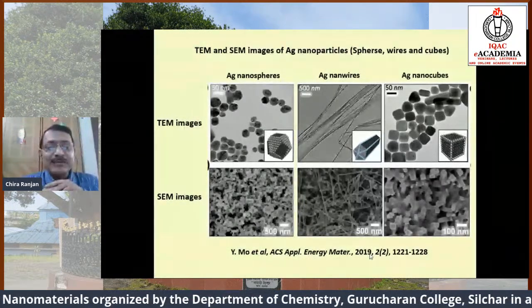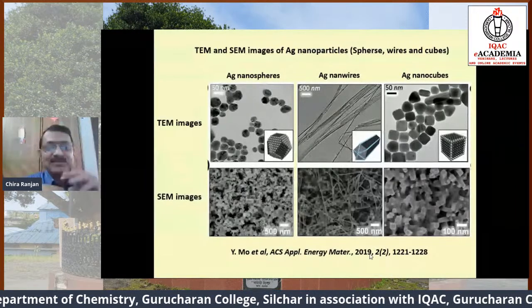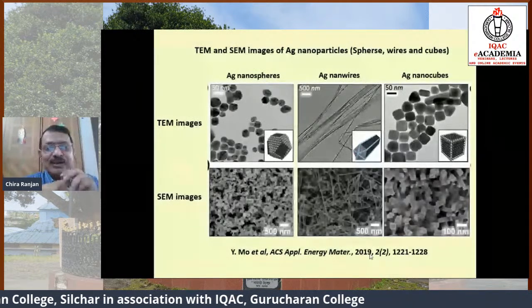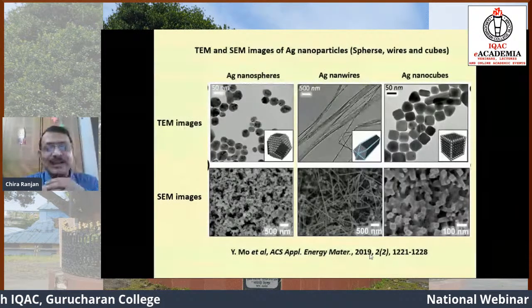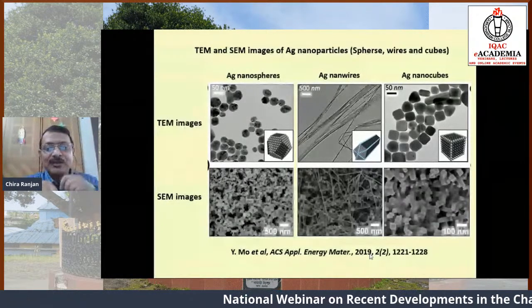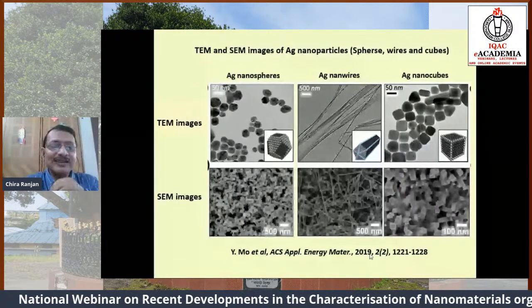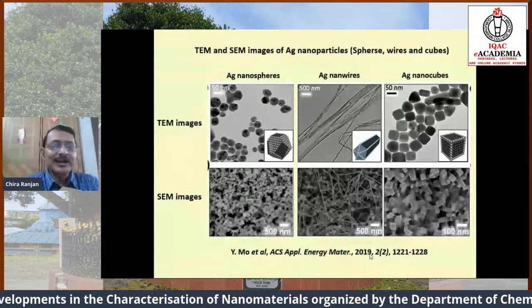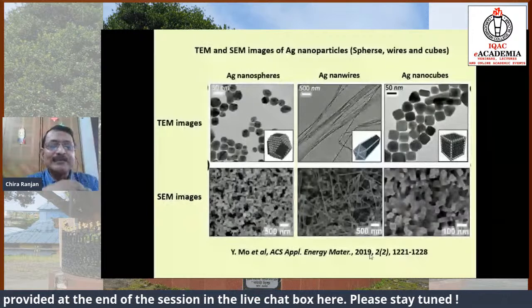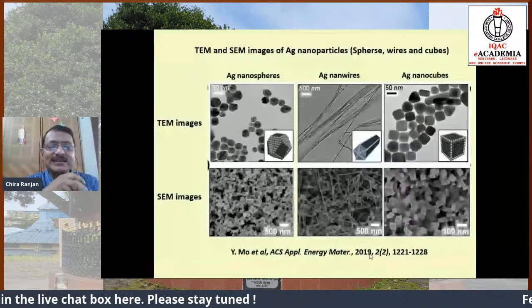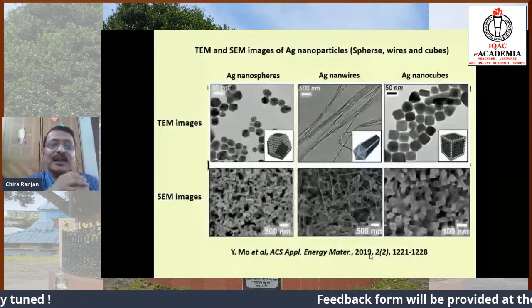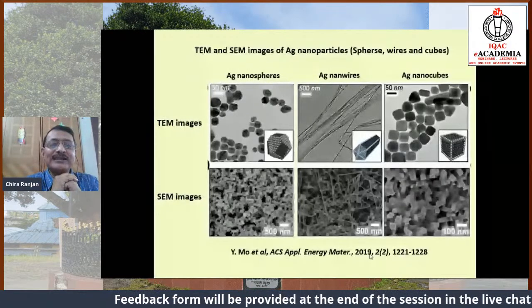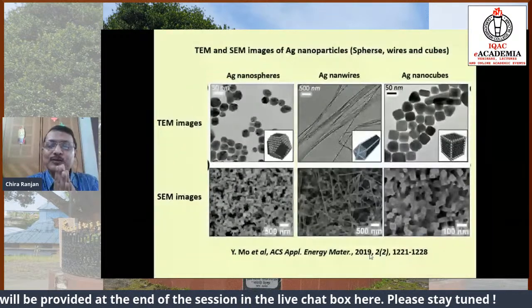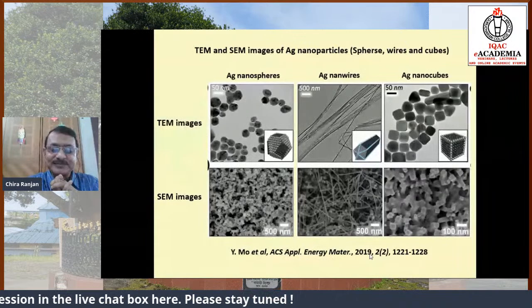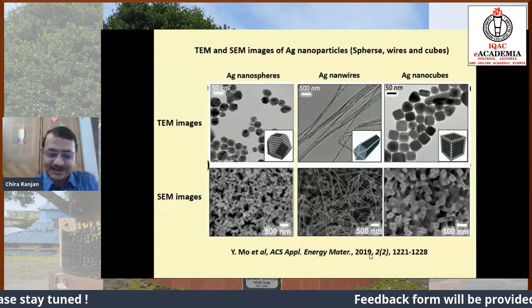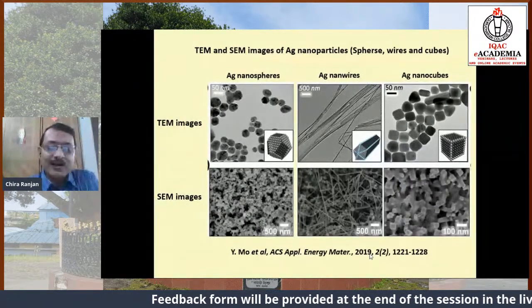In the inset of the TEM images, you can see some pictures showing simulated structures of the nanoparticles, either a polygonal shape or a tubular shape or a cubical shape, but these are not images taken by TEM. These are actually simulated images based on the TEM and SEM images, which are put inside as an inset to understand what the structure actually looks like. So we can see how beautifully we can decipher nanospheres from nanowires and nanocubes based on both TEM and SEM images. This work was published just last year, and we have taken these images from that particular paper in ACS Applied Energy Materials.